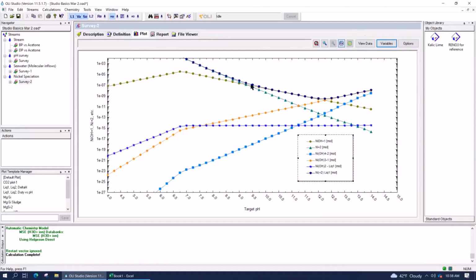Problem is, if you get low enough pHs, nickel is no longer passivating, so you need to have chrome in there to form a chrome passive film. And that gets into the more material science part. I'm not an expert in that, but that kind of gets into what passive films are important under what conditions. Any questions about that?